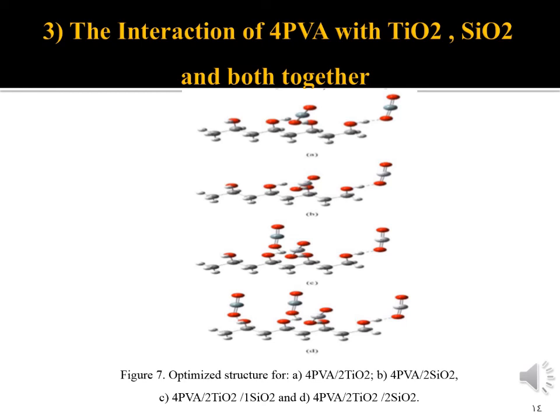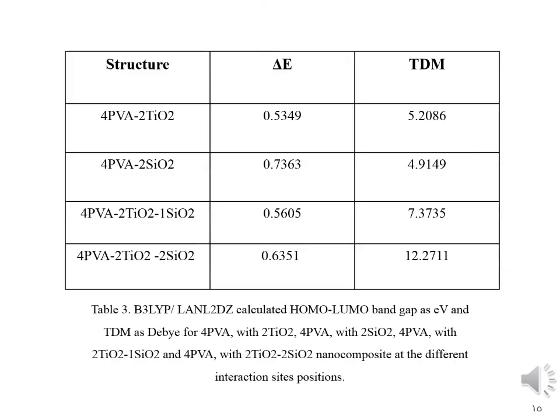Figure 7 presents optimized structures for Figure A polyvinyl alcohol to titanium dioxide, Figure B polyvinyl alcohol to silicon dioxide, Figure C polyvinyl alcohol to titanium dioxide to 1 silicon dioxide, and Figure D polyvinyl alcohol to titanium dioxide to silicon dioxide. For Figures 7a and 7b, Table 3 presents the calculated values of HOMO-LUMO energy and total dipole moment. The HOMO-LUMO energy gap decreased to 0.535 and 0.7363 electron volt for polyvinyl alcohol to titanium dioxide and for polyvinyl alcohol to silicon dioxide respectively.